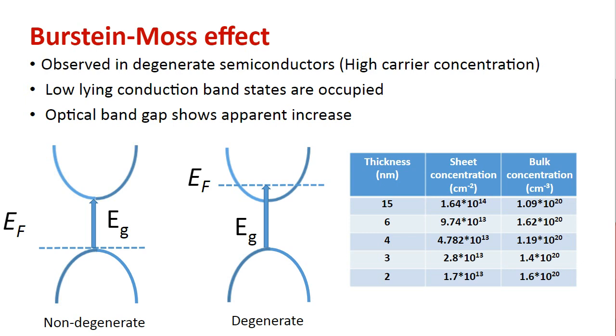Now in bismuth selenide, what we think is happening is that the valence band is occupied and the lower part of the conduction band is also occupied. That's why it's called a degenerate semiconductor. So when an electron from the valence band has to jump to the conduction band, it cannot jump into one of the occupied states. It can jump only to an unoccupied state, so it has to jump all the way over the Fermi level in the degenerate semiconductor. So you can see there is an apparent increase in the band gap. Instead of measuring 0.3 eV that we expect for a non-degenerate semiconductor,